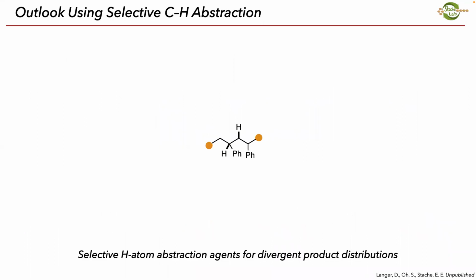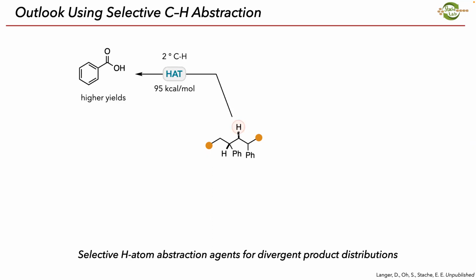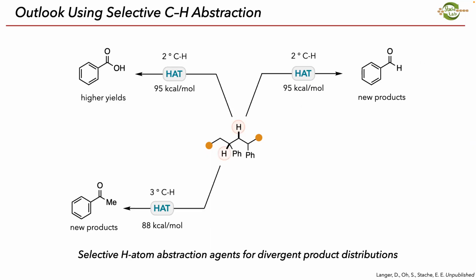And so this is really where we're taking this chemistry: can we get selective H atom abstraction so that we can change our product distribution so we can access some of those other commodity chemicals, which also have even more value than benzoic acid. So for example, can we abstract this secondary CH bond and drive this to higher yields of benzoic acid? Or can we change the conditions such that benzaldehyde doesn't get oxidized, and we can isolate that product? If we abstract the tertiary CH bond, we can turn this into acetophenone instead of benzoic acid. So now we've changed that product distribution to favor a new product.